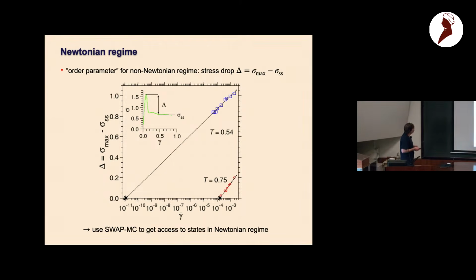And this we do here. Of course, for 0.75, we have access to the Newtonian regime, and we plot this delta as a function of the shear rate. We see that we land here at a shear rate of the order of 10 to the minus 4, and so below here, we expect a Newtonian response.